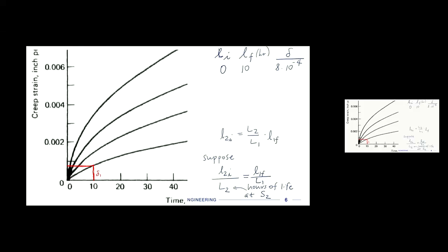So this top one is y equals, I'm going to write this compactly, 0.0026 natural log of x minus 0.0022. Okay, so it's just a fit. I basically took 10 points on each line, used a plot digitizer, and then fit a logarithmic function to it. They all fit fairly well.